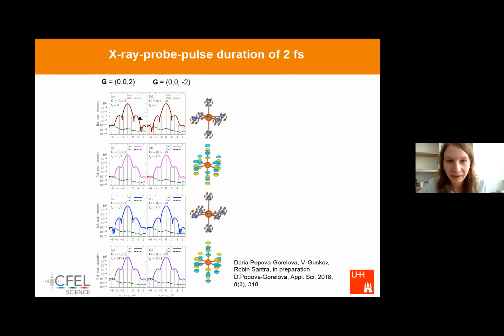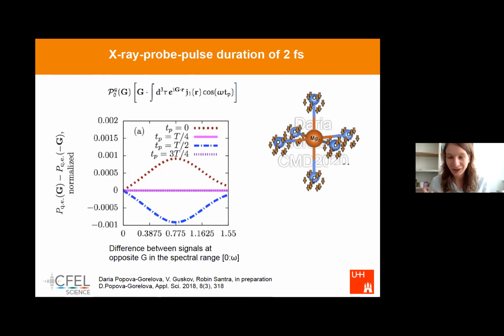And we see that at the time when the currents are at maximum, this break of the symmetry is maximum. When the probability current density is 0, then the signal is centrosymmetric. And this is not just an observation, we could also prove theoretically that the signal is really related to the probability current density, and that you can actually extract this probability current density out of the signal.